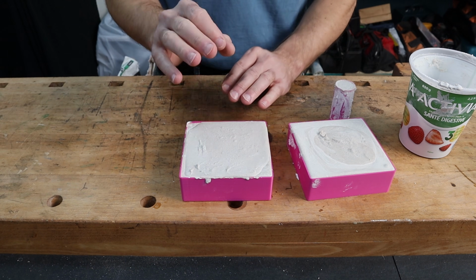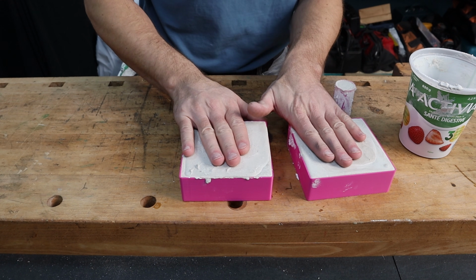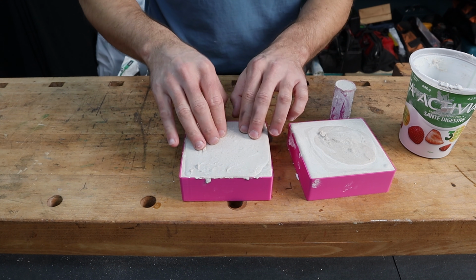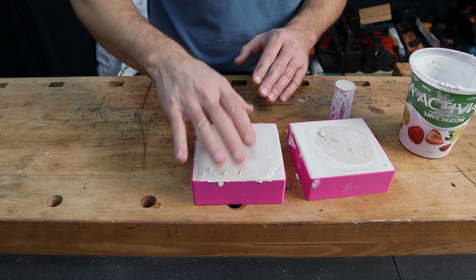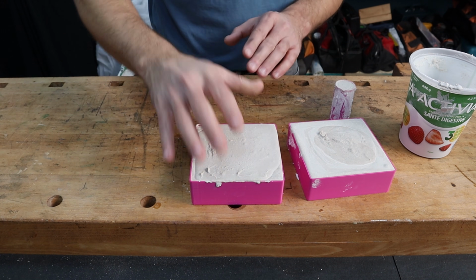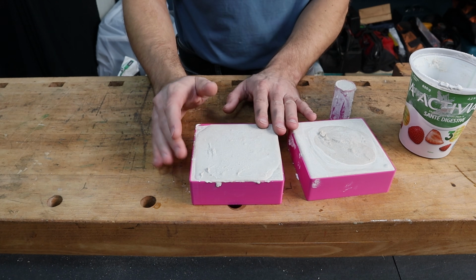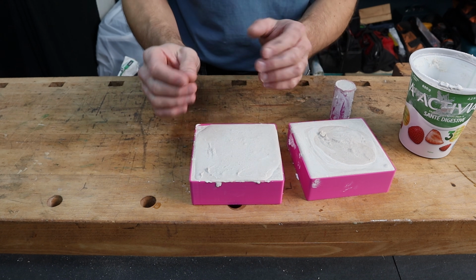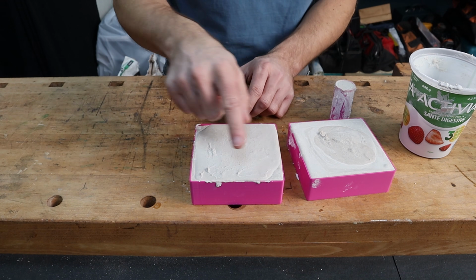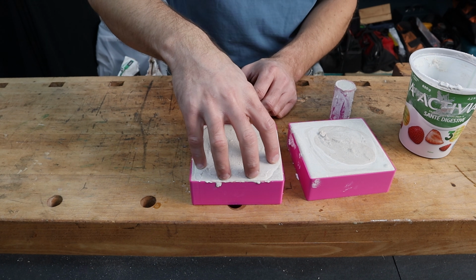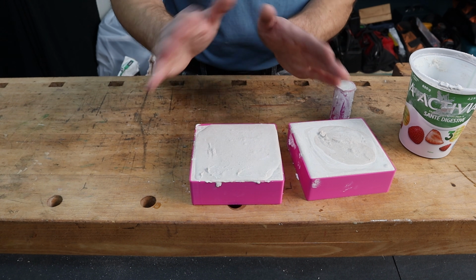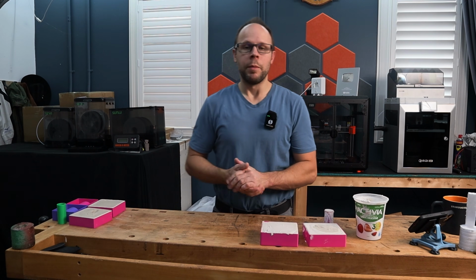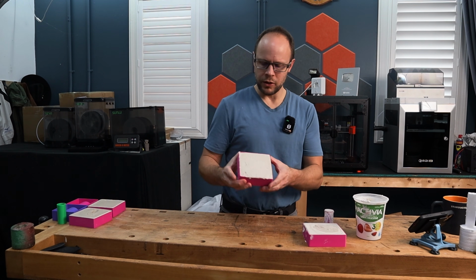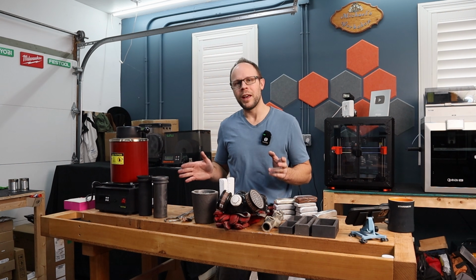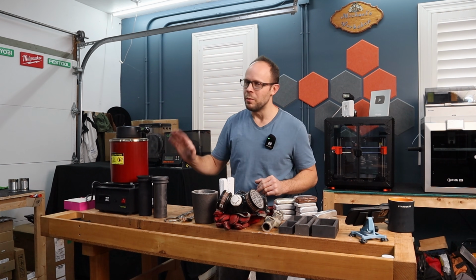So these have been sitting just about an hour or so and they're still warm. So I'm going to let them set for a little bit longer. And then the next step is to remove the plastic. If I were to do this over and over again, I would have designed this differently. I would have had draft angles on here. That way, maybe I spray a release agent and then the plaster can come right out of there, and then we can reuse the mold again. But I didn't want to spend too much time because I don't really know if this is even going to work. So while that plaster is curing a bit longer, we can get set up to melt some metal.